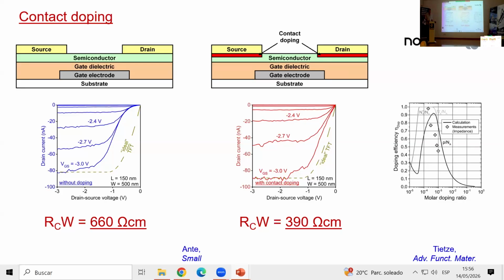And so there's a fundamental difference between introducing dopants in inorganic semiconductors, where they immediately contribute, where basically the contributions are 100%. Every dopant we put in contributes 1 charge. In organics, that's not the case. And in fact, if we continue to put more dopants in, the efficiency will actually drop, as you can see in this graph, right? And so this is a huge impediment to utilizing contact doping, which is why we basically stopped using contact doping at all, because it also has some detrimental effects. It lowers mobility and everything else, right? So we basically stopped contact doping.